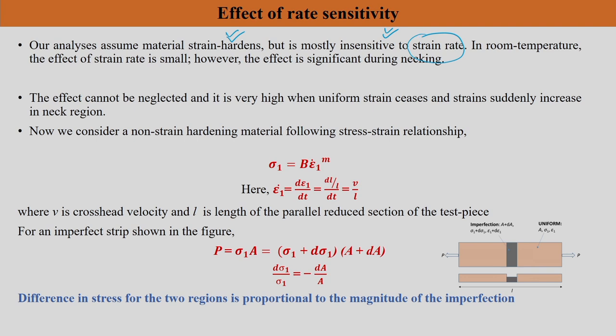That assumption can hold at room temperature, but the problem is that once necking starts, the effect of strain rate becomes significant during the localization or necking process, even at room temperature. So we cannot actually neglect the effect of strain rate, because once necking starts there is going to be an unstable increase in one of the strains, leading to material failure.